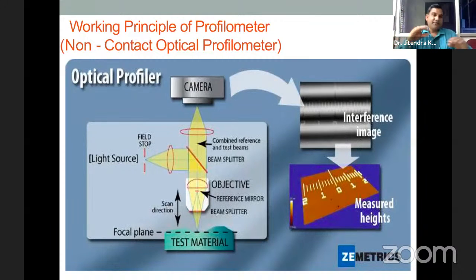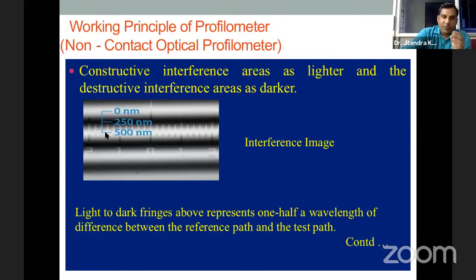If you have some cavity over the surface, then first on the top surface your fringes will form, and the bottom surface fringes will form at last. In that way you can also analyze the step height with this profilometer. So this is the basic principle of the profilometer: the difference of interference between bright and dark fringes gives you the surface topography, surface roughness, and also step height.